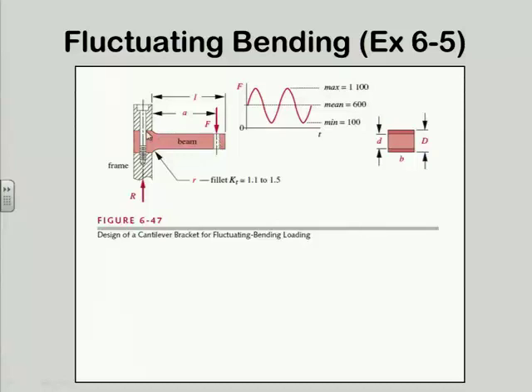And we looked at this beam the other day. I explained why I did this rather than just clamp a straight piece in the wall, because that gives me a stress concentration factor of 2.0. And I can get lower than that by putting a generous radius in there, which is what I did that for. I got it down to 1.2 or something like that. Ranges from 1.1 to 1.5 for that case, according to Peterson.